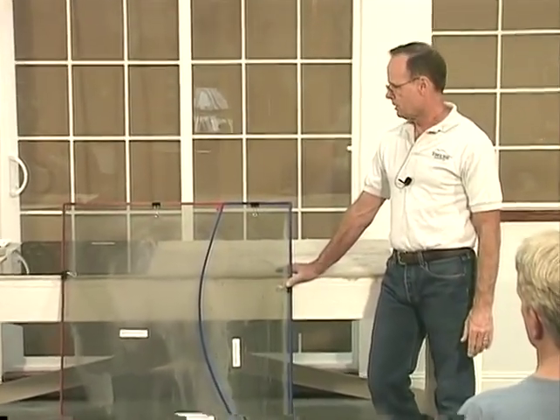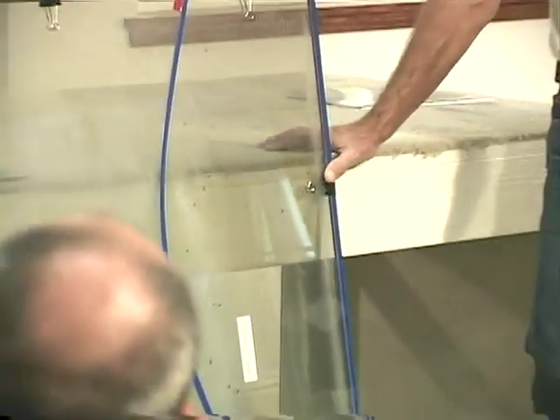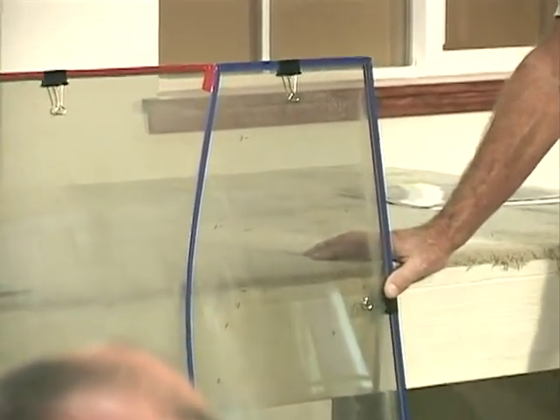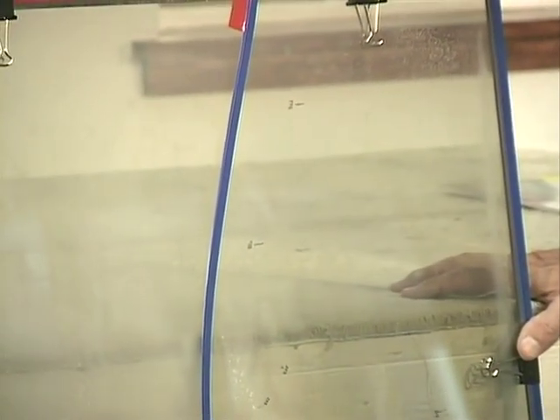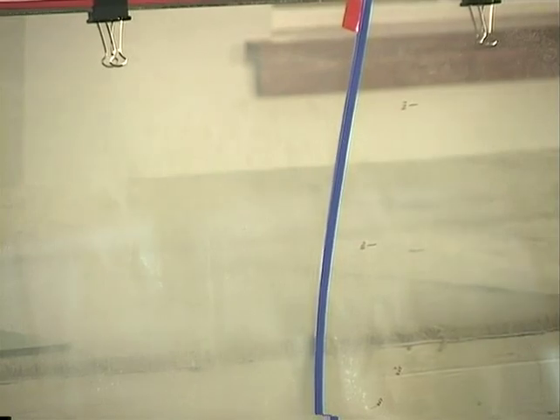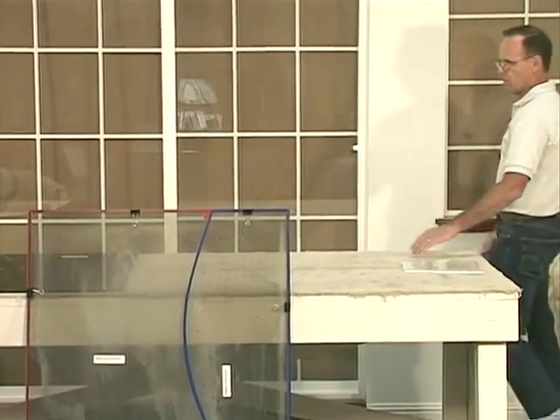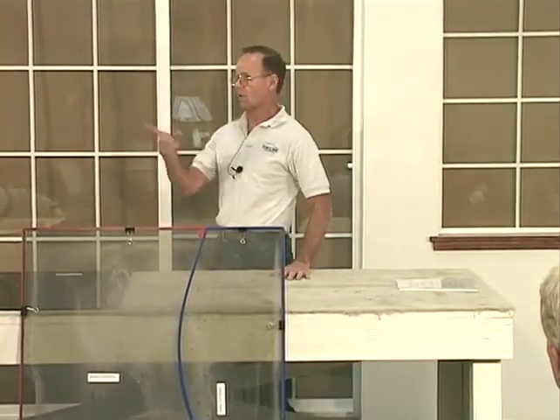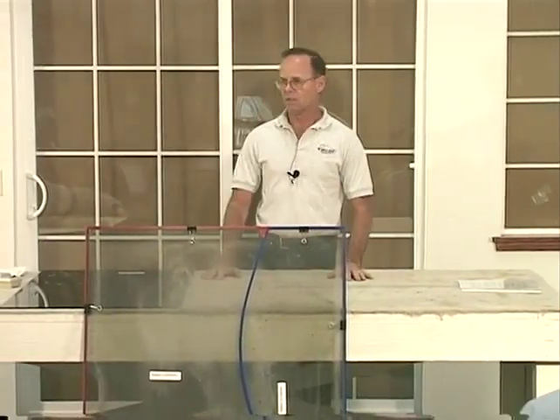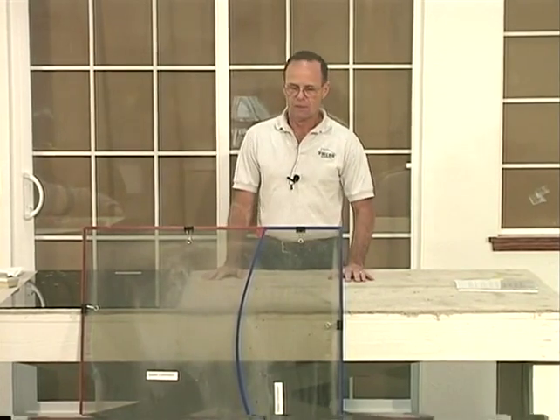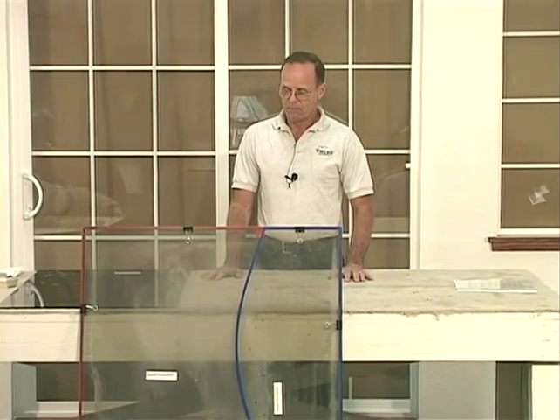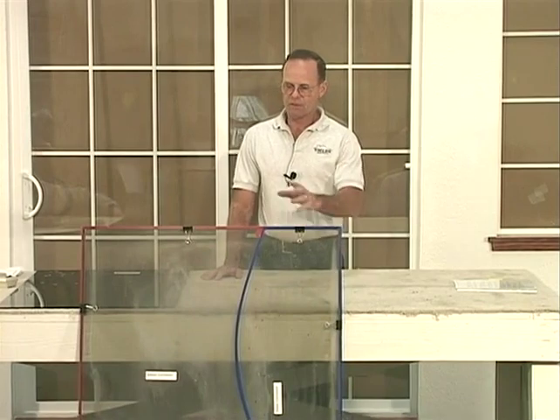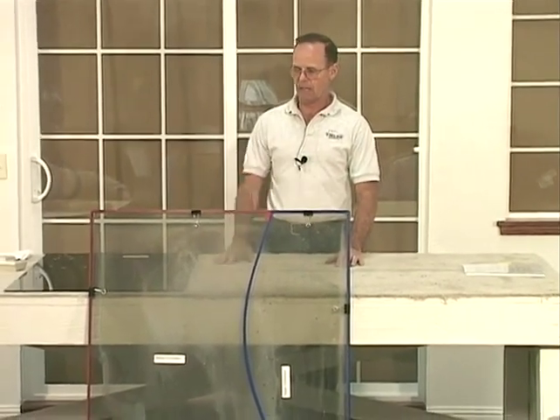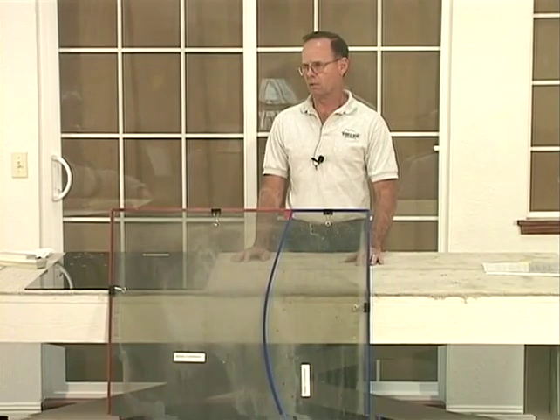And for this to happen, you have to have the moisture, you have to have a stagnant environment, and you have to have time. Without that, you cannot get glass corrosion. That's why all of our windows on our buildings do not corrode, because you don't have that. It happens to this unit because the seals were broke. This I actually took out of my building here because it was such a good sample. And I told them, put a new window in, I want this window. The landlord loved it. But it happened to this window because moisture got in between the glass, and it was a very small amount of moisture.